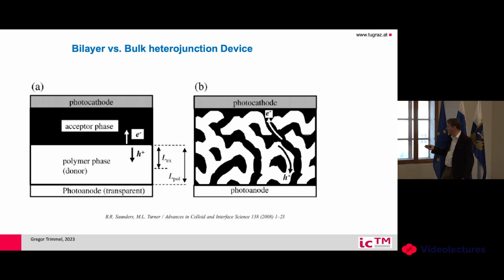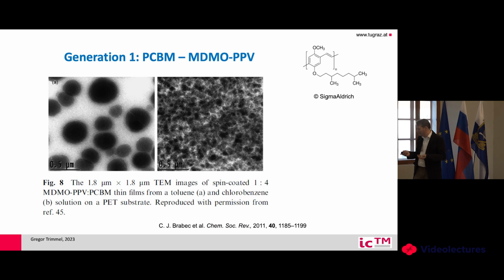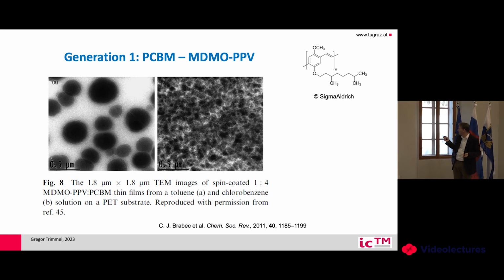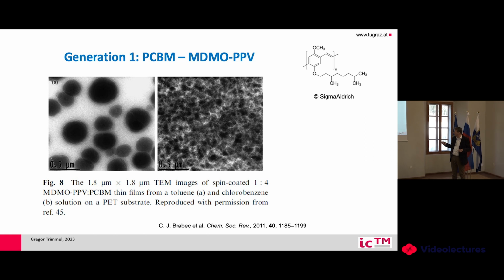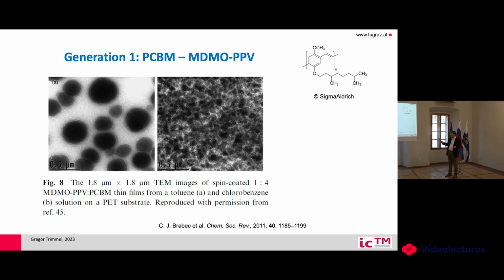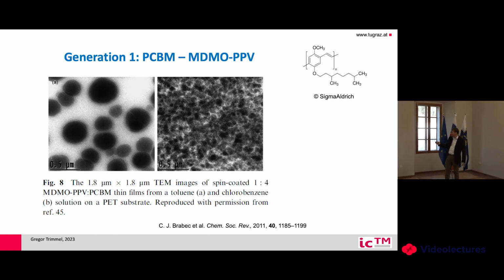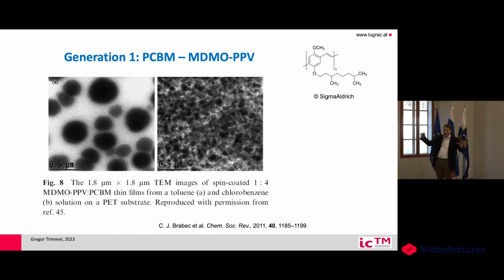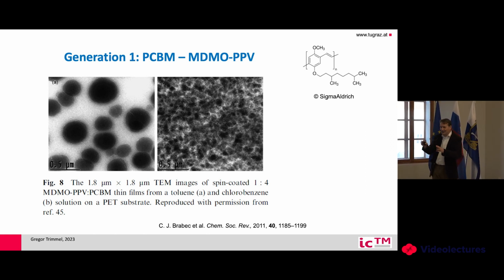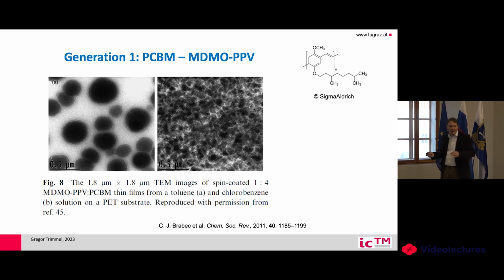I will show you some examples from the literature, how important this actually is. This is one of the first ones, this MDMO-PPV derivative with fullerene. You see, depending on the processing, so this was processed from toluene, and this was from chlorobenzene, very similar solvents, but differently. And I think you can see just visually that you have here very large agglomerates, and here you have very nice smaller agglomerates with higher surfaces. So, you can of course also think which was more efficient. This one was much more efficient. Yeah. With some numbers, I show it on the next slide.